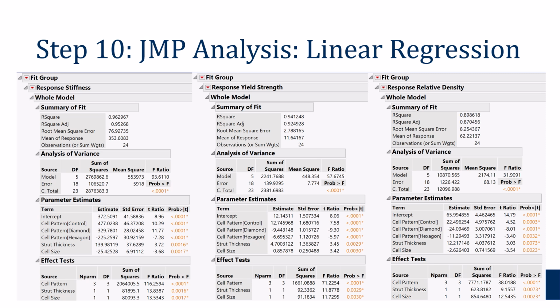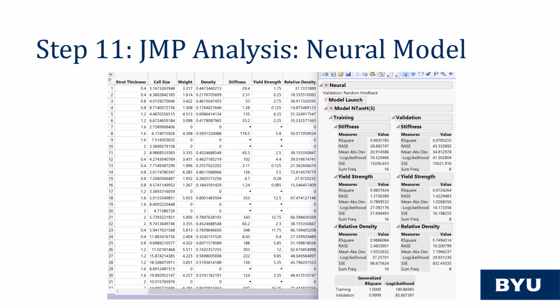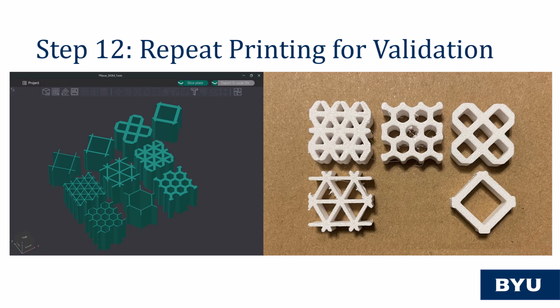The linear regression model demonstrated a strong fit to the model as shown by a high R-squared value as well as a relatively low root mean square error for each output. The second model of fit was a predictive neural model using three levels. Again, this model demonstrated a good fit to the data as shown by the high R-squared values of 0.9936 and 0.9785. However, the sum of squared error values were higher than ideal for each of the three outputs. The formulas for both models were saved, and the relative errors between the predicted and actual values were calculated.